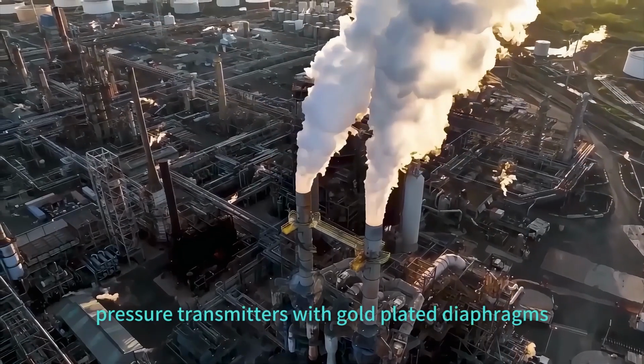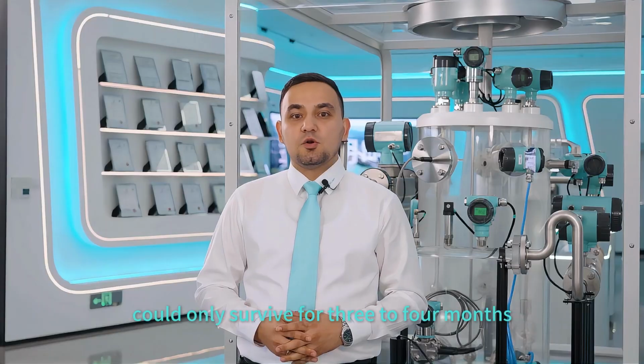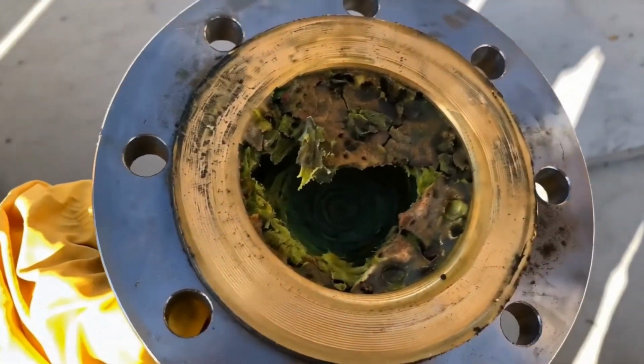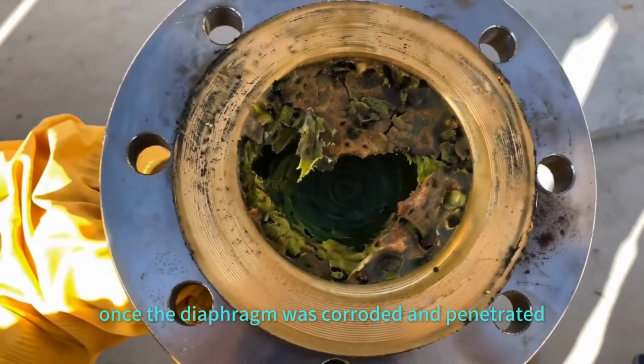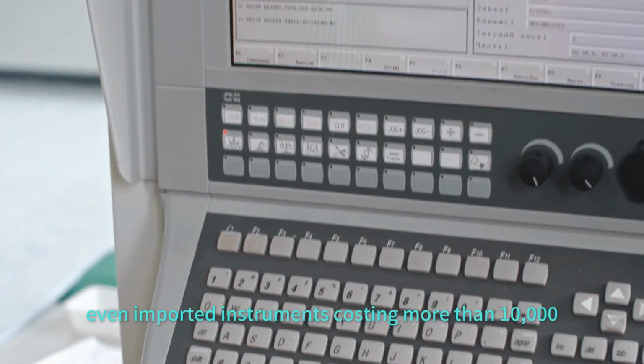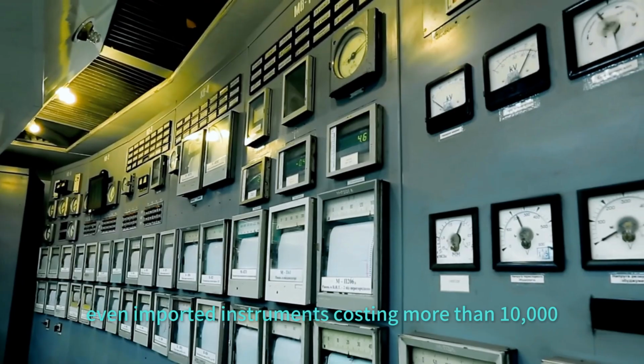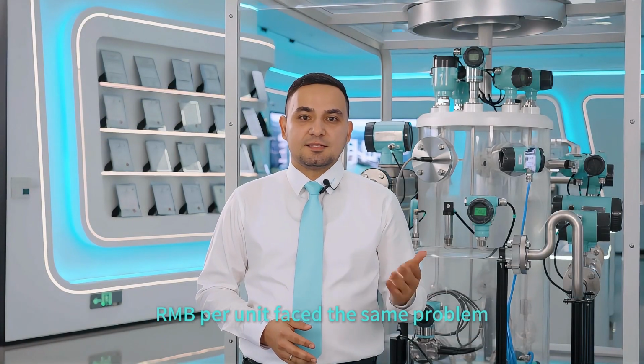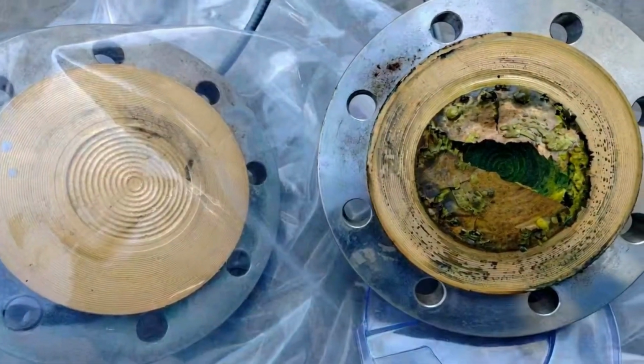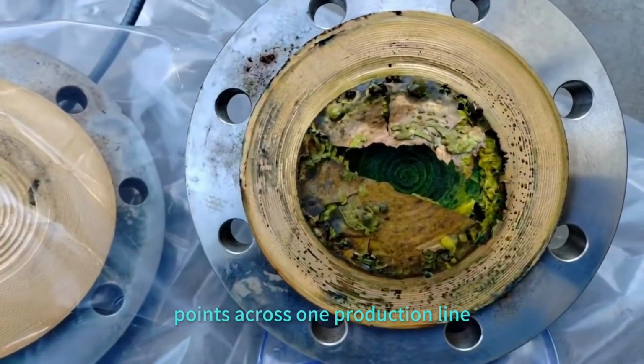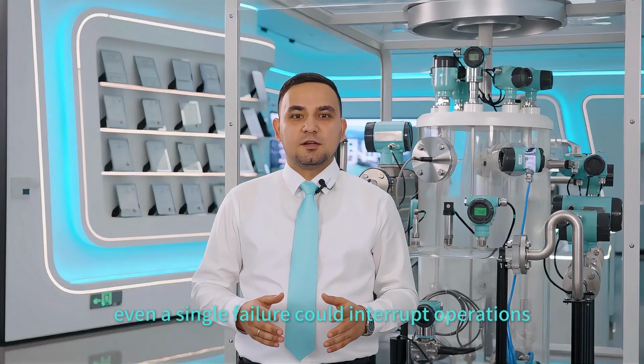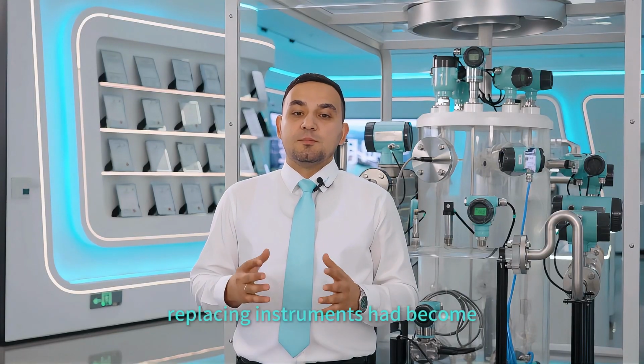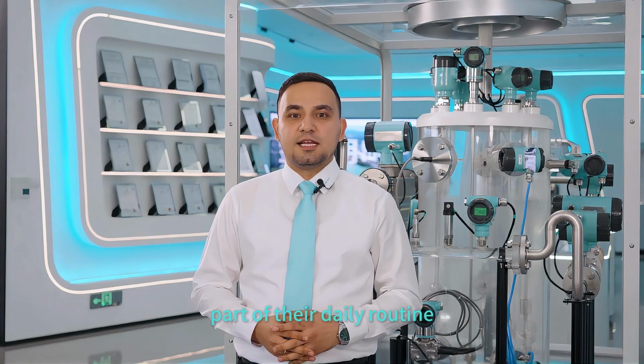Their medium is highly corrosive hydrochloric acid combined with high temperatures. Under these conditions, pressure transmitters with gold-plated diaphragms could only survive for 3 to 4 months. Once the diaphragm was corroded and penetrated, the measurement data was lost. Even imported instruments costing more than 10,000 RMB per unit faced the same problem. Replacement was still needed every 3 to 4 months. With hundreds of measurement points across one production line, even a single failure could interrupt operations. Replacing instruments had become part of their daily routine.